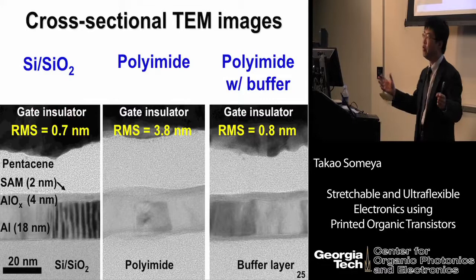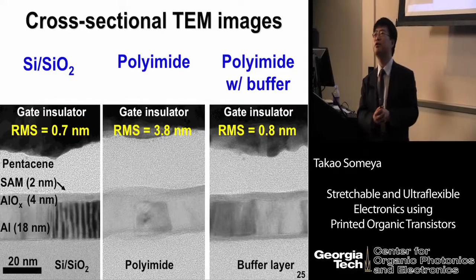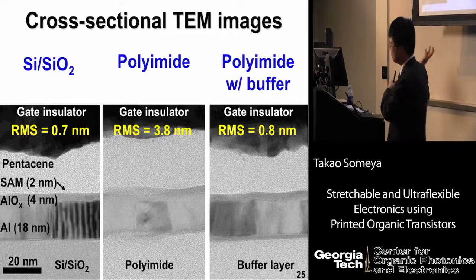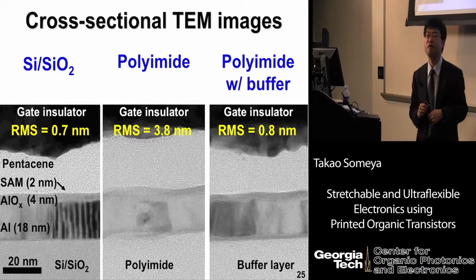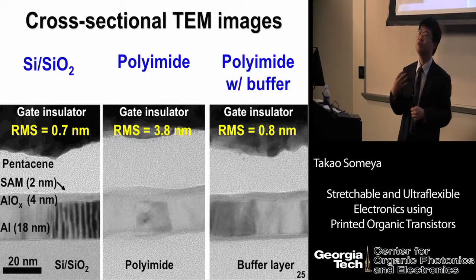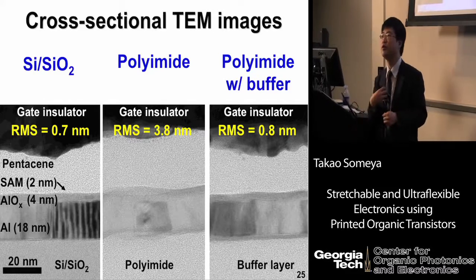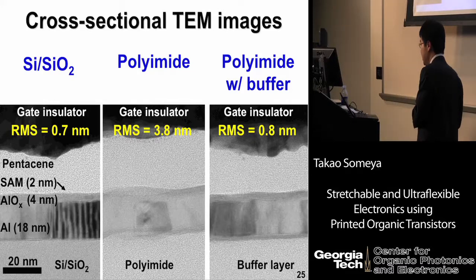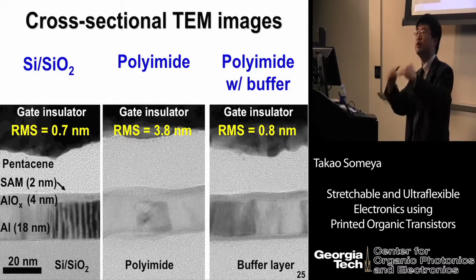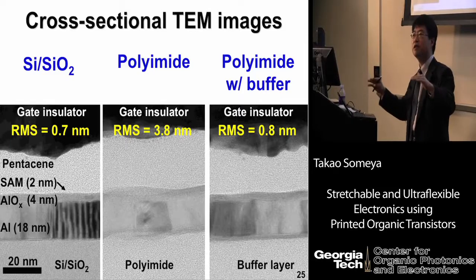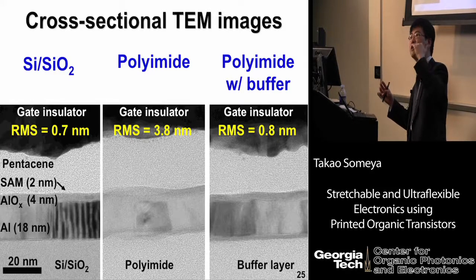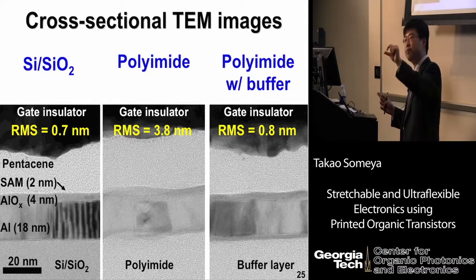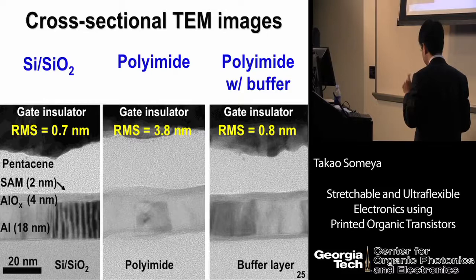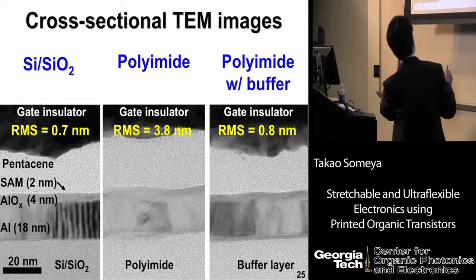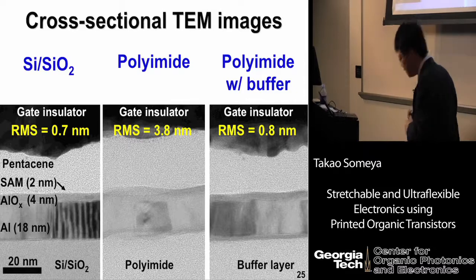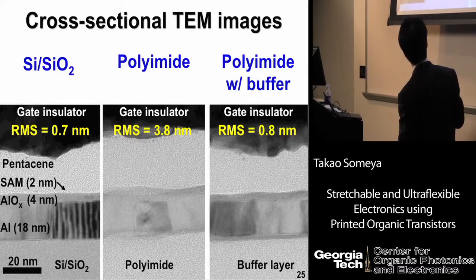So of course, the formation of self-assembled monolayer is a well-known phenomenon, and all chemists know the self-assembled monolayer. However, one of the most important contributions from our group is something like this. The monolayer is nicely formed on quite flat surfaces like glass, silicon oxide, or some other smooth surface, with a nice monolayer on an atomically flat substrate. However, if we try to make the same self-assembled monolayer on plastic, here is a problem.